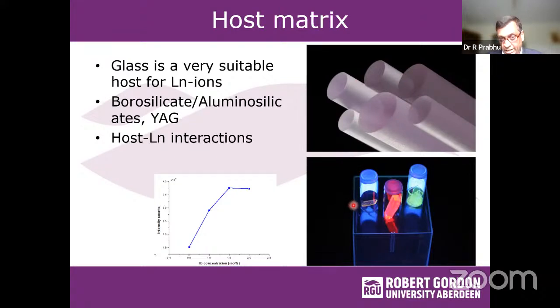Again, this is one of the Nd:YAG-based crystals. And these are some of the glasses we developed in our own laboratory by doping different rare earth elements into the glass matrix of borosilicate glass. By changing the concentration of the rare earth elements doped in the material, we can change the intensity of fluorescence from these glass materials. Based on the host and the dopant, we might have to strike a balance to get maximum fluorescence based on the doping possibility. In this case, you can see maximum doping for Tb is around 1.5 mole percent.